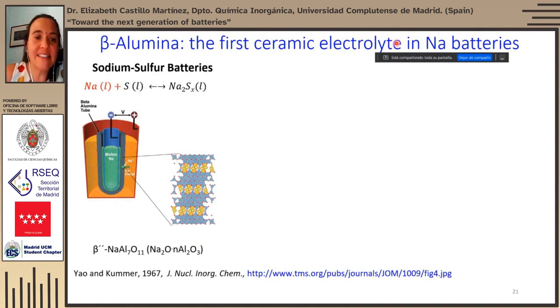We know that ceramics can also be good ionic conductors. And indeed, the first sodium sulfur commercial battery, made by the Ford Motor Company in 1967, contained a ceramic beta alumina electrolyte, which transferred the sodium ions from a molten sodium tank to a molten sulfur tank. And this was at temperatures of 300 degrees.